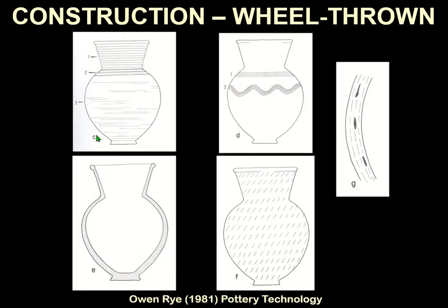So other lines of evidence, those very fine lines, incisions that are made as the wheel is going around. Here you can see designs incised on the outside on a moving wheel, far too regular than could be used on not a wheel. The way that the vessel gets progressively thinner as it goes up. Here is an idea. These are the inclusions again, and because it's thrown up as it's been going around, all the inclusions are angled like this in the side of the vessel, and they're parallel to the sides of the vessel.